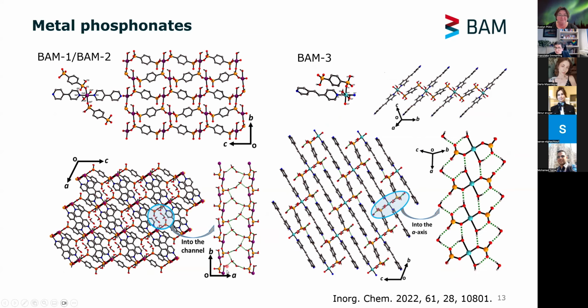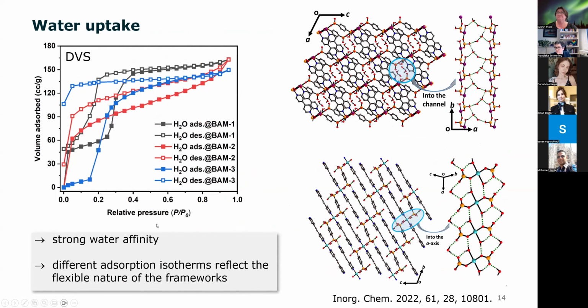And you can see here the coordination environment in the different MOFs obtained here. And we also can see that we have something here that would be good for proton conduction. We have different channels where our water molecules could more or less hop along. So these are either structural BAM 1 and 2, and this is the other version. We then performed dynamic vapor sorption testing to see whether there is an affinity to water in these compounds, and this is a given. You can see a bit of hysteresis, so the compounds are not super rigid, so there is a bit of a reaction to the guest molecules.